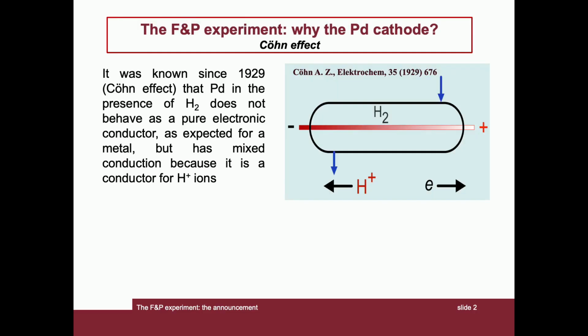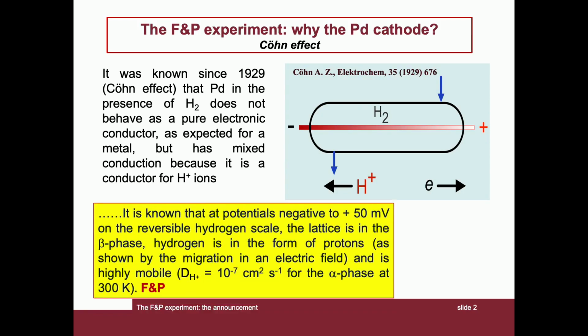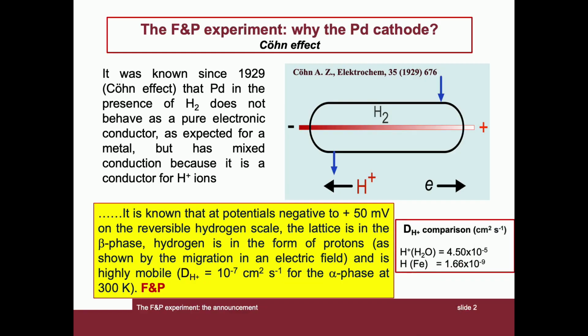The Fleischmann and Pons experiment. Why the palladium cathode? It was known since 1929 as the Cöhn effect that palladium, in the presence of hydrogen, does not behave as a pure electronic conductor, as expected for a metal, but presents mixed conduction because it's a conductor for hydrogen ions. The consideration reported in the article by Fleischmann and Pons is highlighted here, in which the proton state of hydrogen inside palladium and its mobility given by the high value of the diffusion coefficient are underlined. This state is unique in cases of a metal-hydrogen interaction.